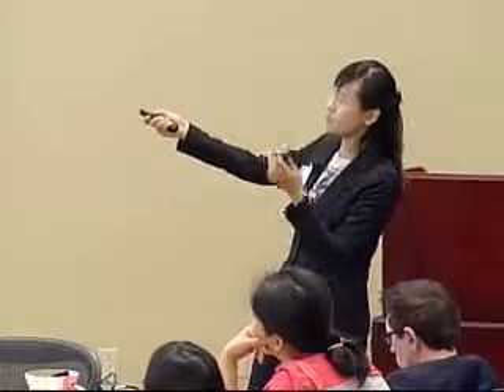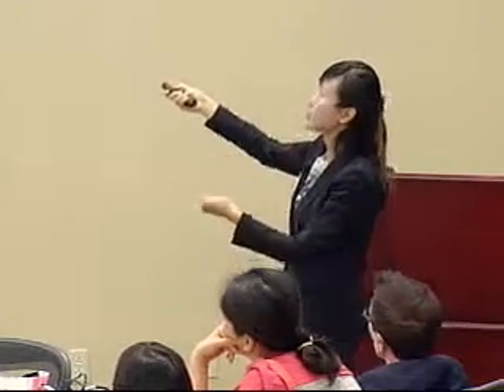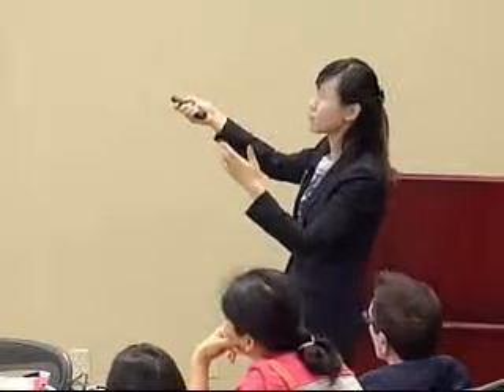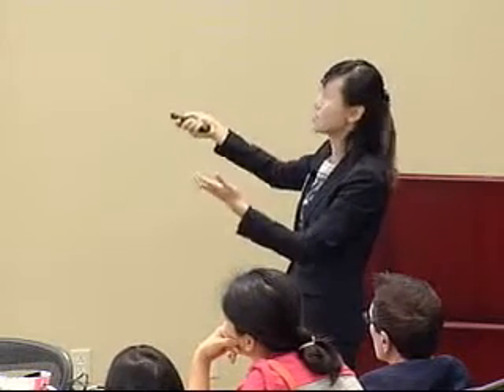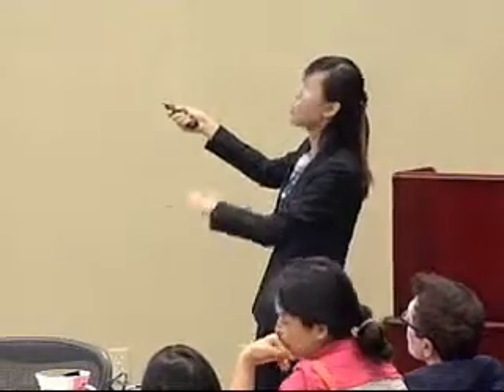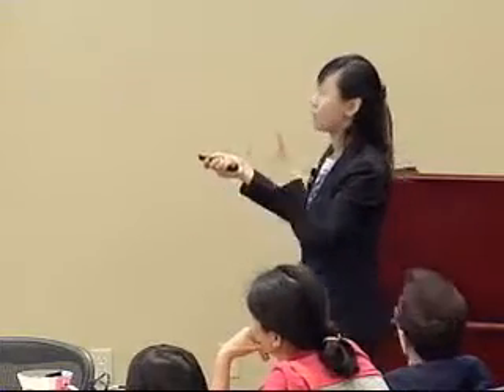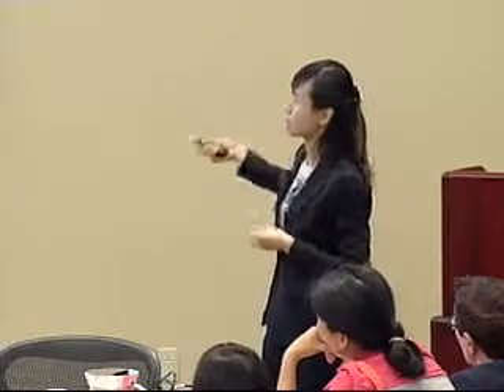So first of all, when we try to mount something onto the skin, again, I look at the mechanical performance. Relatively stiff and thick polymer, it can still conform to my wrist, but once I deform, they detach very easily. Whereas when we reduce the stiffness, reduce the thickness, even by not changing the interface, none of these have any adhesive on the interface. Pure van der Waals weak interaction. Because the driving force is low, the delamination didn't occur at all. Of course, this whole system could be experimentally measured by a more rigorous configuration and modeled.